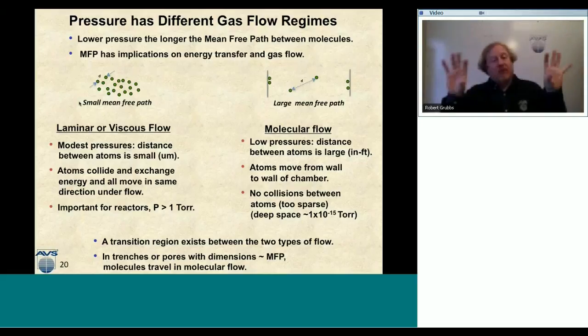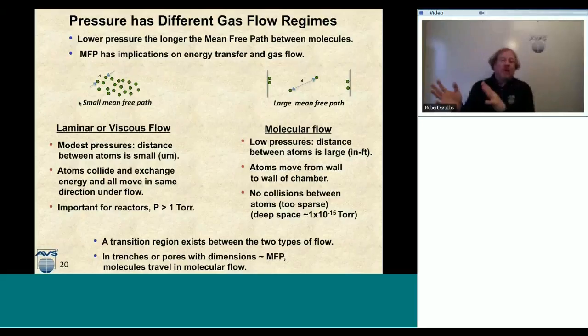And sometimes, depending on the geometry, I get this laminar flow condition. And this is going to be very important in our ALD reactors, where they're at a pressure of about a torr, and we want to be able to transport chemical precursor very efficiently to our sample surface. And so we want to be in the laminar or viscous flow regime.